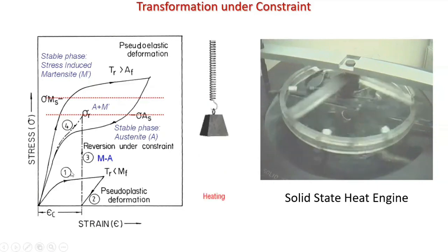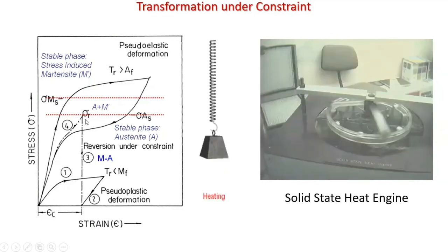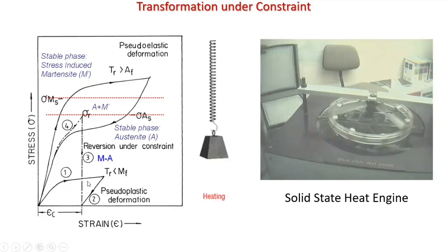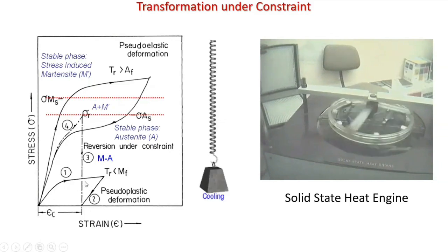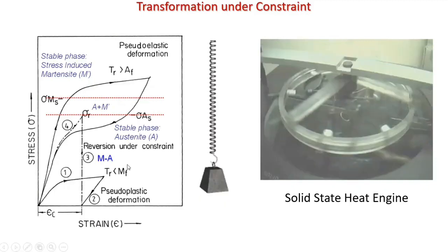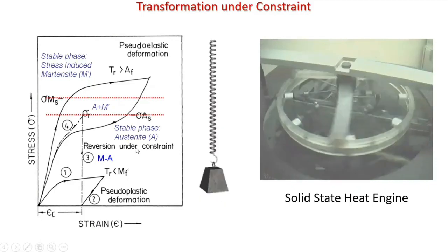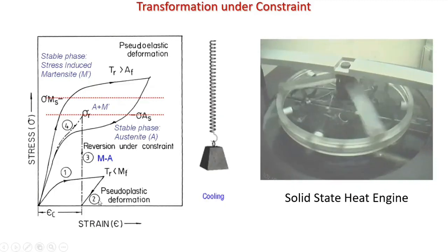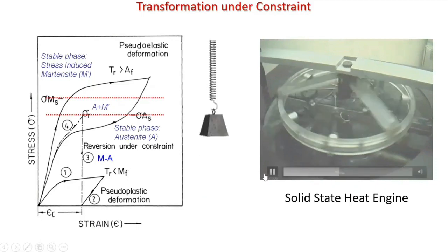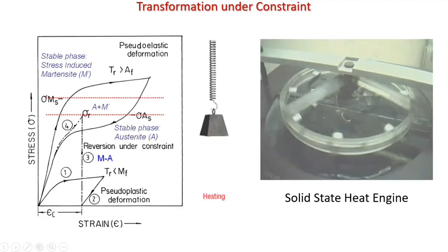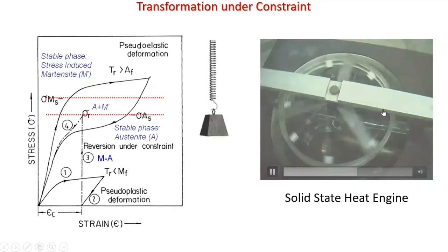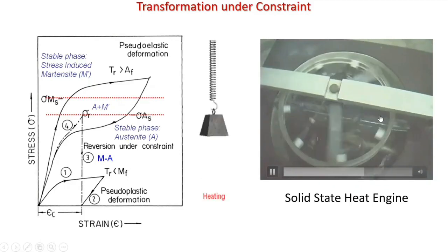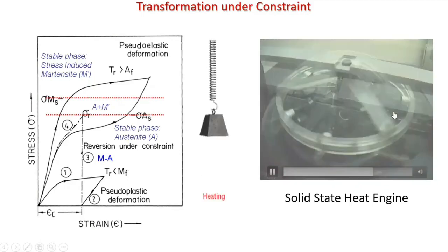And what you see is that between these two, a nickel titanium shape memory loop is actually being deformed. In the cold water, it is being deformed. In the hot water, it recovers. So you deform it in the cold water, and when you pass it on to the hot water, a big stress develops. That stress is about 500 MPa, and the stress required to deform is only 100 MPa. So what you've effectively done is converted heat into mechanical energy. You input this deformation, you input heat, and this is what you get back.